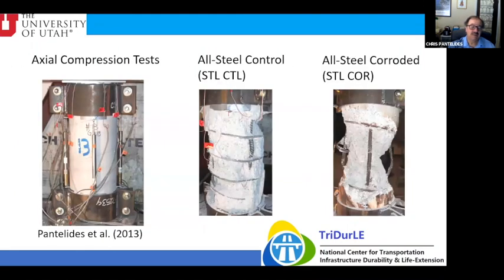So after we did the corrosion test for about 11 weeks, we did axial compression tests. As you can see here, we put some steel collars to guarantee that fracture would happen in the mid height of the column. And here you can see the results. The results of the compression test also help you to see the corrosion inside.